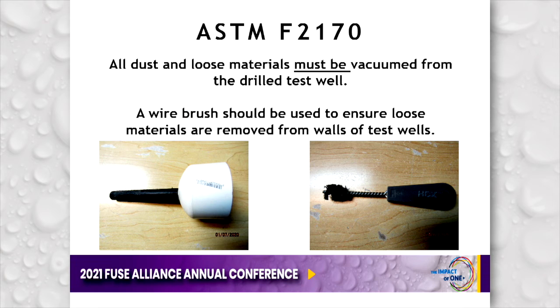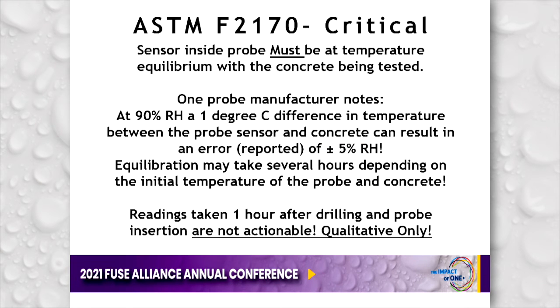Also important, critically important, that all the dust and loose material must be vacuumed from that drilled test well. We need to be using a wire brush to ensure that all the loose material comes off the walls of that test well, and then we need to be able to vacuum to the bottom of that test well. Any dust in there is likely going to cause disruption of the ability of the probe to read the accurate relative humidity. Also, critical, the sensor inside the probe must be at temperature equilibrium with the concrete being tested.